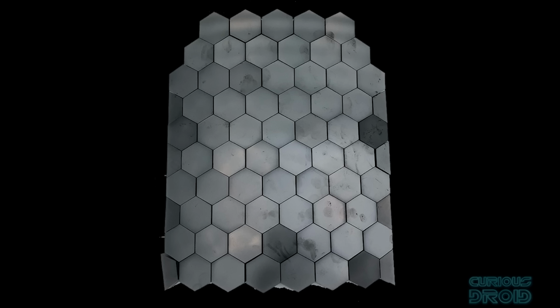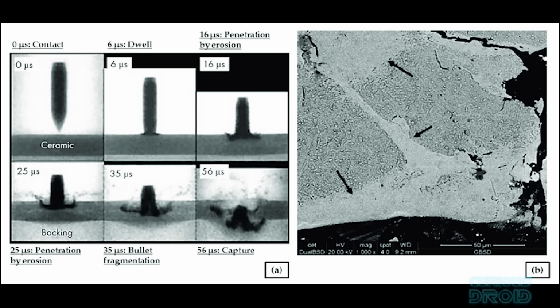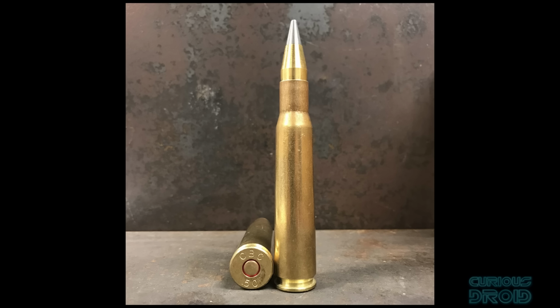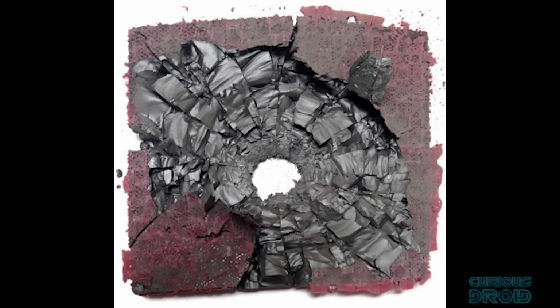If we put hardened armor plates made from something like boron carbide in the Kevlar, the steel jackets around the bullets aren't hard enough and will break up. Putting a tungsten tip on the bullet will cause the ceramic plates to break up, because although the plates are hard, they are not durable enough to withstand the impact toughness of tungsten, and they shatter due to brittle failure. A similar thing happens with bombs and bunkers.